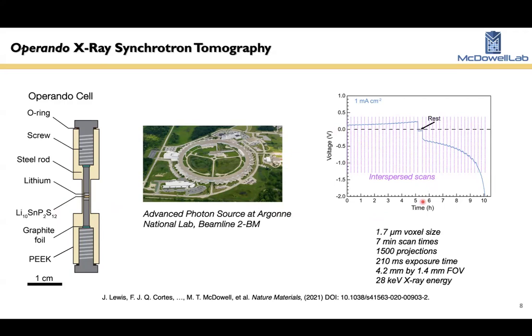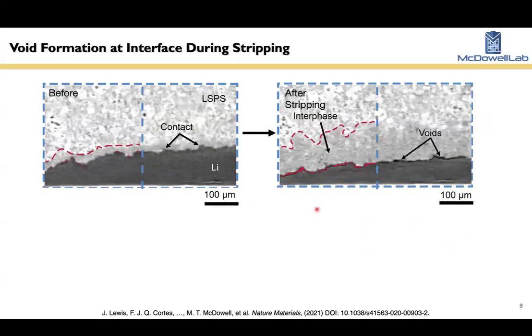So the way that tomography works is you take a bunch of 2-dimensional projection images, and then you use an algorithm to reconstruct those into a 3-dimensional data set that contains all the image information in your material or your cell. And for these experiments, we achieved about a 1.7 micron voxel size, a 3D pixel. So the resolution is on that order, and we have scans every 15 minutes. So what does this data look like?